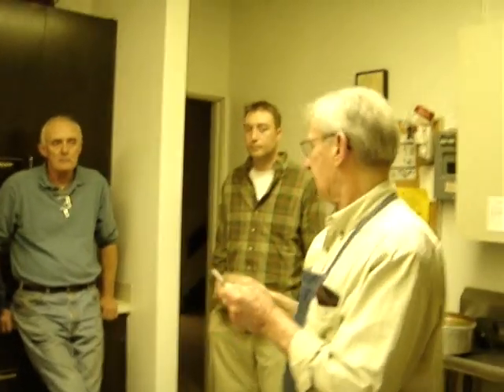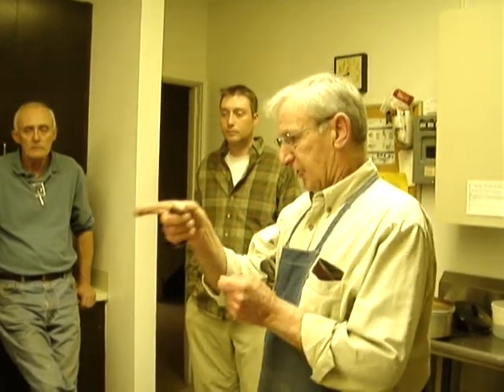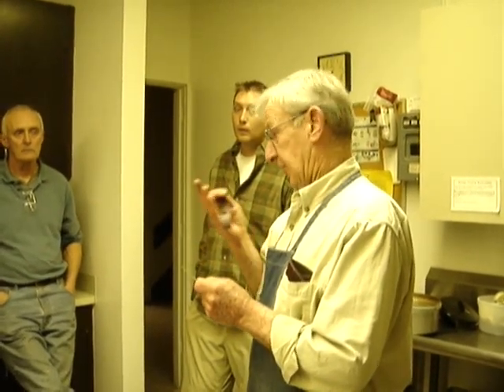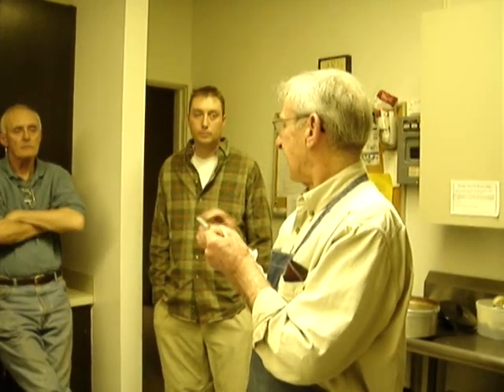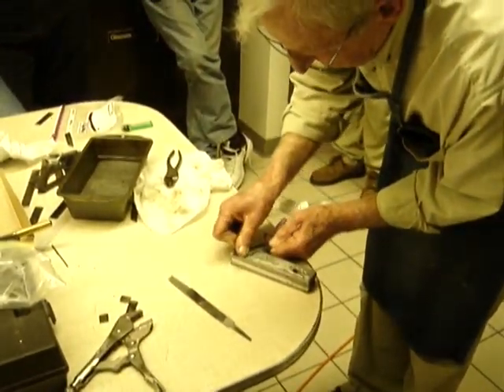Anything 52 or more is pretty good because it's hard enough that it'll hold a good edge for you, but not so hard that it could chip and crack. The blade itself will flex, but you don't want it super hard. It'll get very, very sharp, but then the cutting edge can chip. You get little minute chips in it, just the way he just broke that one. Same thing with a good German cutlery, kind of Rockwell is